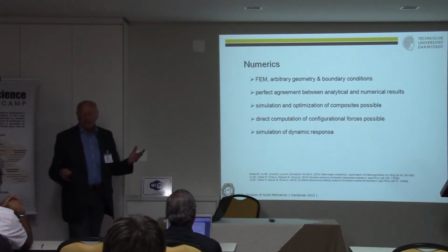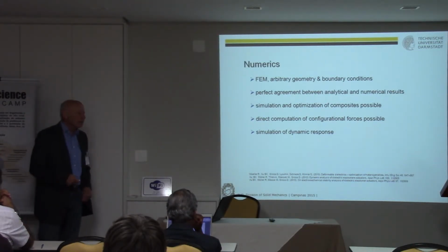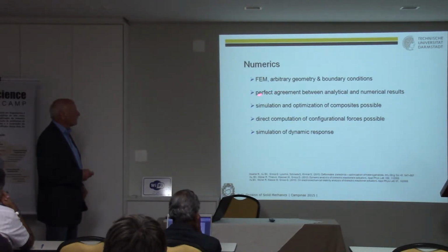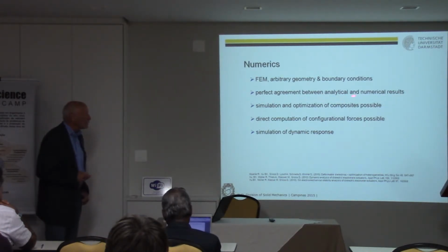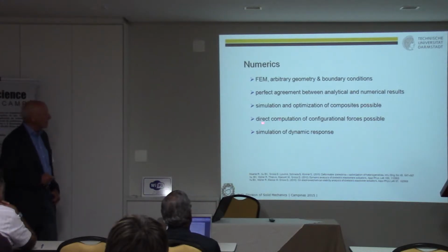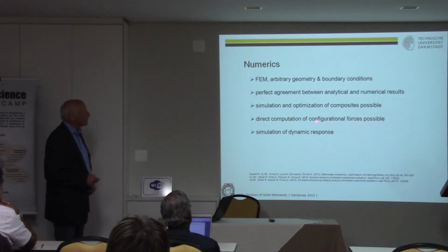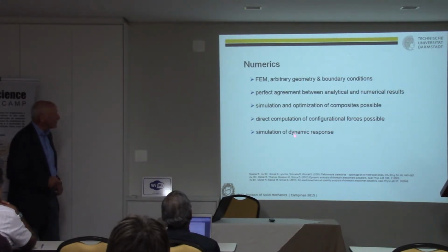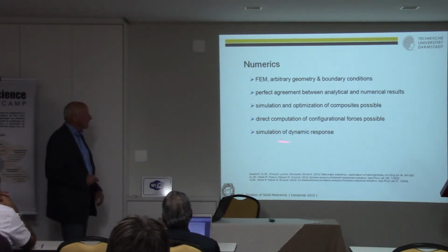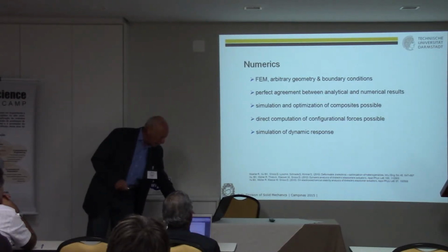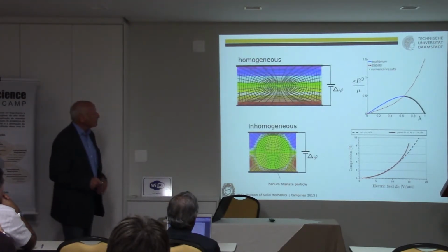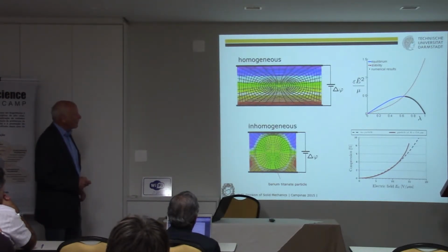And this you of course can also do with numerics, for instance with the finite element method, for then you are not restricted to the geometry and the boundary conditions. But what you see is a perfect agreement between analytics and numerics in this case. And what you can do with simulation, you can optimize your composite, and you can also compute configurational forces if necessary. You also, and this we have done, simulations of the dynamic response.